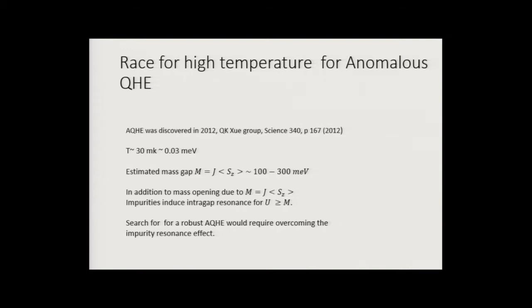And I think the best example would be the ones where you have very little perturbation in the vicinity where the gap should open up. The example I showed you, the counterexample to what I was saying, is the one where we have a little perturbation in the density of states. This would be a good example. For instance, vanadium in antimony telluride would be a good example. And then the other one, I think, was cobalt.